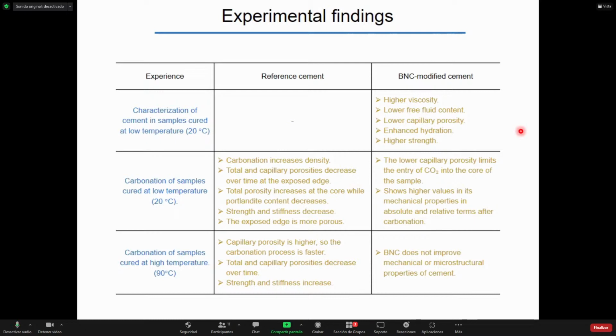When we carbonated this cement, we saw that for all samples, carbonation increased density, that total and capillary porosity decrease over time at the exposed edge, that total porosity increases at the core while portlandite content decreases, the strength and stiffness decrease over time, and the exposed edge is more porous. When we added bacterial nanocellulose, the lower capillary porosity limits the entry of CO2 into the core of the sample. And it also shows higher values in its mechanical properties in absolute and relative terms after carbonation.